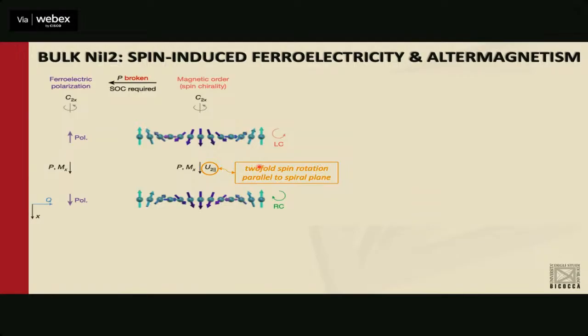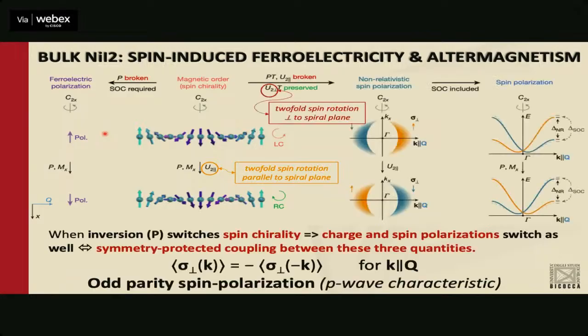What is the catch here? It's a bit technical, so I will not discuss it in detail. But I told you so far that a spin spiral generates ferroelectric polarization with a certain direction. Then I switch chirality, and I generate the opposite polarization. That is the multiferroicity of nickel I2. Now it turns out that nickel I2, based on its symmetry properties, also produces a spin splitting. So despite being an antiferromagnet, the band structure is split.